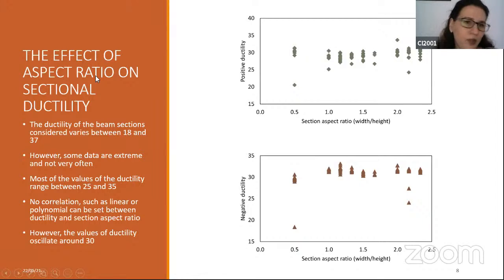Now, the parameter that we expected to have the greatest effect on ductility was the aspect ratio, and also this was the one parameter that we could draw the strongest conclusion from if we were to find relationships. However, from these graphs, we have here the positive and the negative ductility. The beams had non-symmetric sections, so we calculated the moment curvature relationships both in the positive and negative directions. So we obtained two, positive and negative, ductility values. So we can see here that there is no clear relationship.